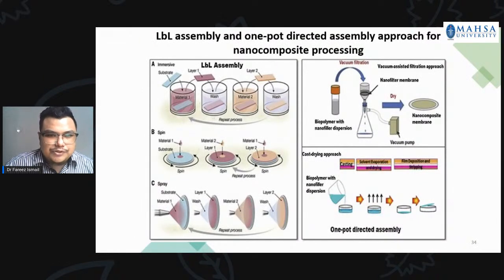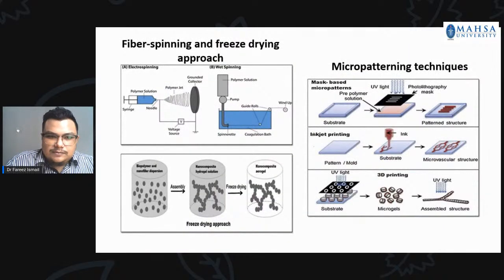So this is another approach where we can process the nanocomposite using layer by layer assembly, either through immersive, spin or spray method, as well as this one pot directed assembly approach and the cast drying approach. Other than that, there are fiber spinning or freeze drying approaches. Fiber spinning, or called electrospinning. We actually have one paper already submitted to Cellulose, currently under review, using a rubber nanocellulose method prepared by this electrospinning method. And I hope it can get published soon.